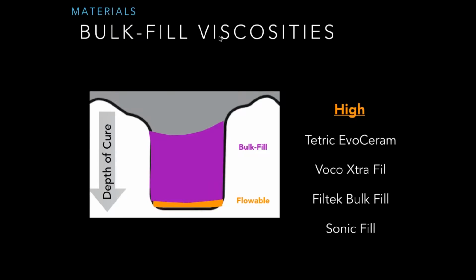Bulk fills in the market today are offered in 2 viscosities, high and low. As you apply what we've been learning here and talk about the flowability, the high viscosity formulations can sometimes be difficult to get adequate adaptation without a flowable liner foundation. Pay close attention to the shrinkage stress because it varies between materials, and some may have unacceptable levels which may compromise the integrity of the restoration or that foundation. Also be careful with different bulk fills to make sure the depth to which these materials can be properly and thoroughly cured. Very, very important.